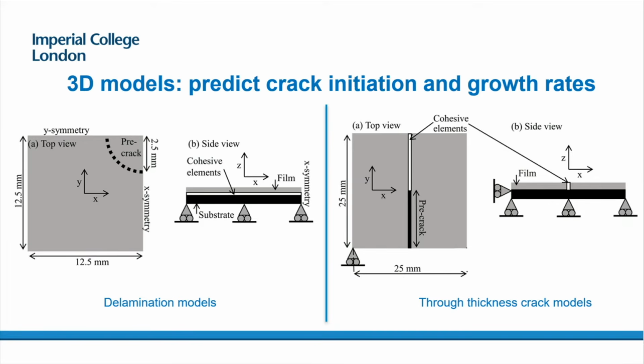This is the model that we use for delamination, the flaking off of the paint. This is a quarter of a painting, and this is the top view. So imagine your painting is this size. We're only modeling a quarter of it. And in the middle here, we have a flaw. We have a crack. We subject this to the fluctuating humidity, and then we see how long it takes for the cracks to start propagating from this initial flaw. And this is the model that we use for through thickness cracks. So this is the cross section, and then the crack is going to go through the thickness, but also it can run along the painting as well.